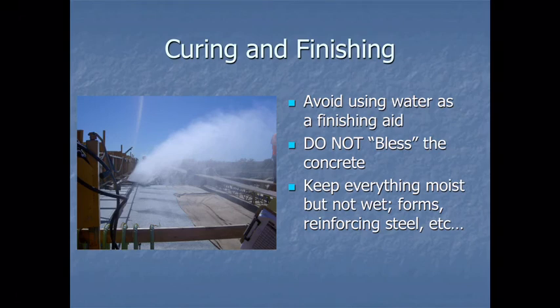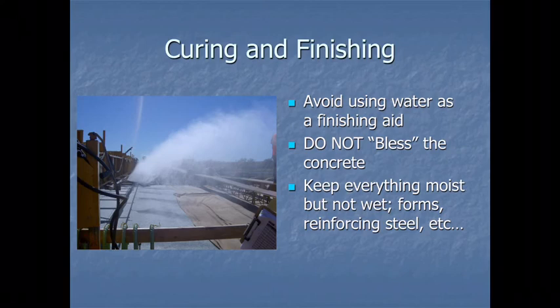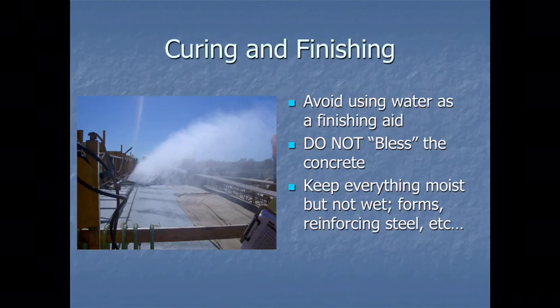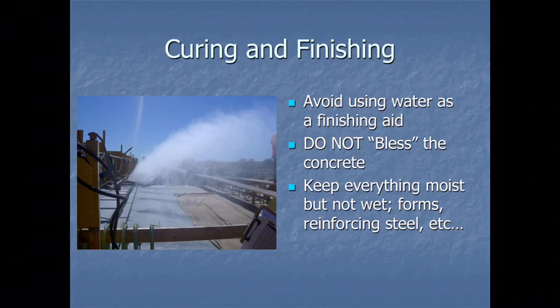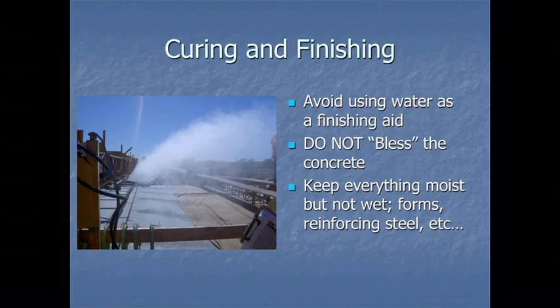Avoid using water as a finishing aid. Adding water droplets to the top may look good initially, but it traps water underneath the paste — and when it cures, the surface delaminates when walked or driven on. If water is added to the concrete surface, it must be in the form of a mist, not droplets. Everything needs to be moist but not wet — forms, especially wood forms, and reinforcing steel should be moist, as concrete benefits from having water to draw in.